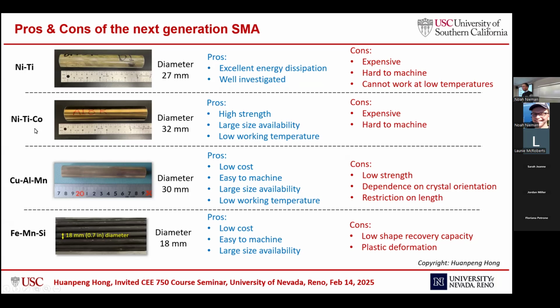And nickel titanium cobalt alloy. The pros of this material are that it has improved strength, it has large size availability, and it works better at low temperature. And the cons of this material are the same: it is expensive and it is hard to machine. So those are the pros and cons.